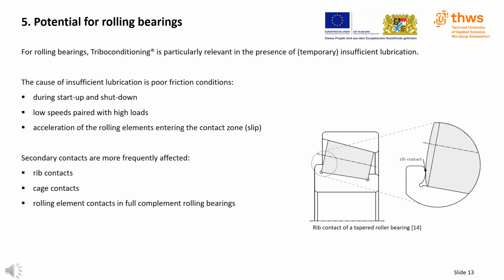For rolling bearings, triboconditioning is particularly relevant in the presence of temporary insufficient lubrication. The cause of insufficient lubrication in rolling bearings is poor friction conditions that prevent the formation of a load-bearing lubricant film. Such conditions exist, for example, during startup and shutdown of rolling bearings. In addition, low speeds paired with high loads can lead to insufficient lubricant film formation. In large bearings, the rolling elements are extremely accelerated when they enter the contact zone, which can tear the lubricant film open and thus also result in solid contact. This is referred to as slip in rolling bearings.